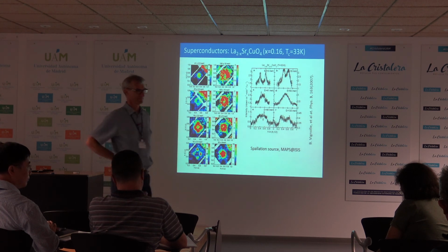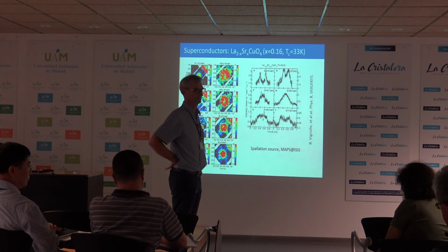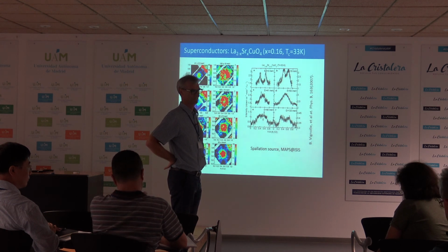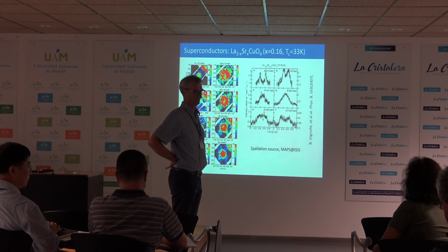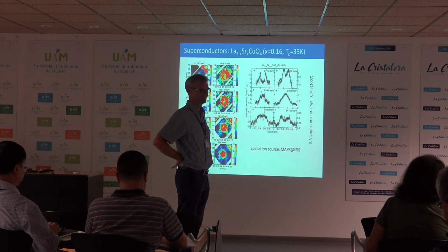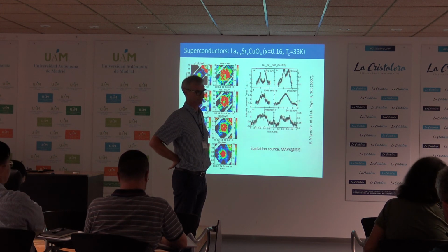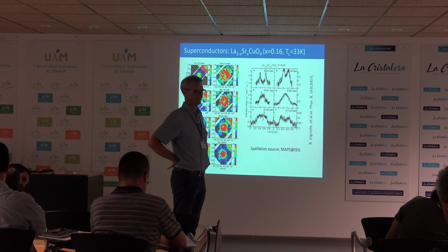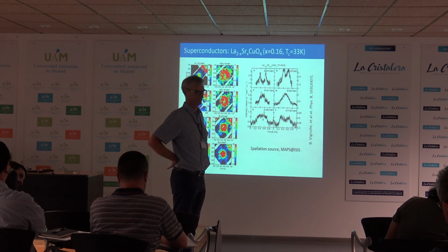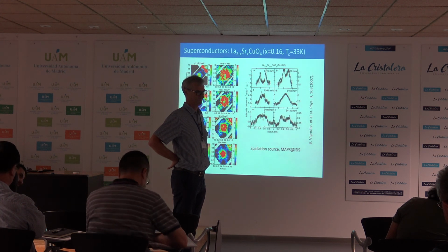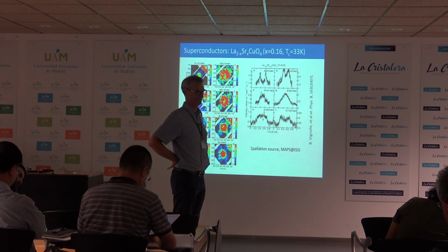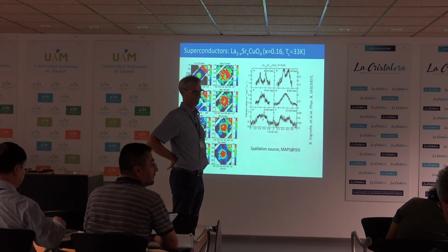I want to come back to the same point, in fact, and your comment on the width of the peak, in what I understand you were referring to as the real part of the susceptibility and the imaginary part. Did I get this right? That's right, yeah. If I take your damped oscillator picture, and all I do is give my harmonic frequency a Q dependence, as we would like to do to get some description of these magnetic fluctuations, then I have a correlation length, the static correlation length of that system.